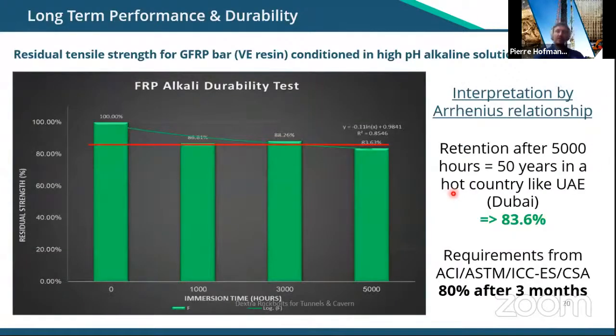So typically, this is the kind of behavior we would see. So this is a test we have conducted even recently. While GFRP will lose some performance quickly after, let's say, 1,000 hours, 40 days, we quickly plateau, and as we can see, it would generally retain about 80% of its strength over a long period of time. So while most standards require at least 80% after 3 months, what we've tested at Dextra, we were able to maintain this 80% plus even after 5,000 hours. That's almost 7 months.